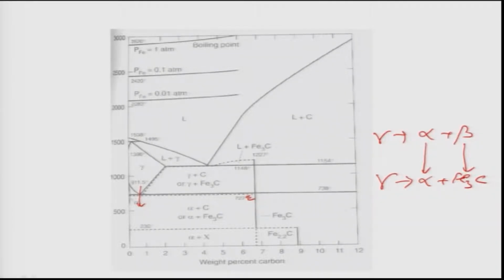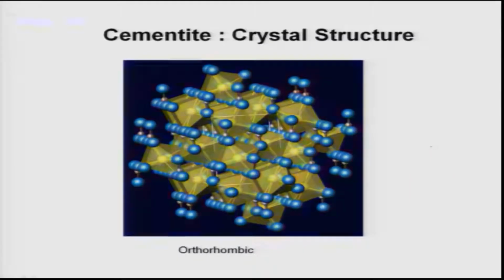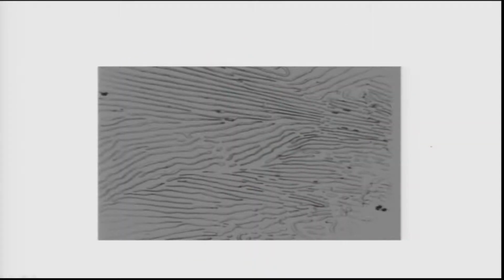As one phase, gamma, which is present at high temperature, undergoes a transformation leading to the formation of two phases, the microstructure is very simple here. It will be a lamellar one, like you have seen for the eutectic. Let me first explain the microstructure and come back. This is a typical optical micrograph of pearlite, which you normally see in plain carbon steel. As you see here, it consists of two phases, one which is white and continuous, the other like a plate. These are plates having different orientations in the microstructure. Normally these plates are Fe3C, the carbides, and the continuous phase is alpha.